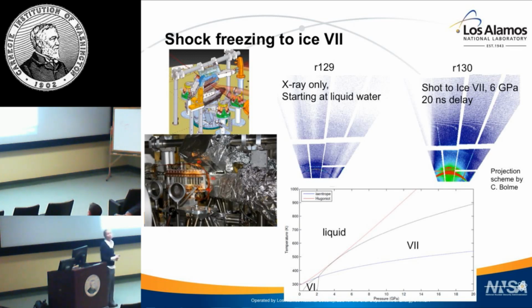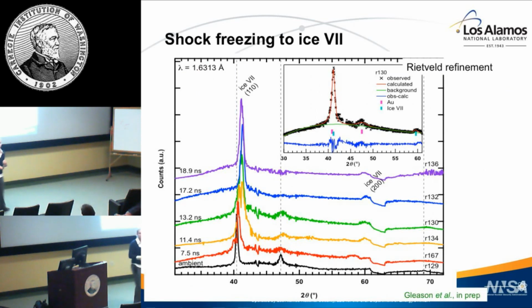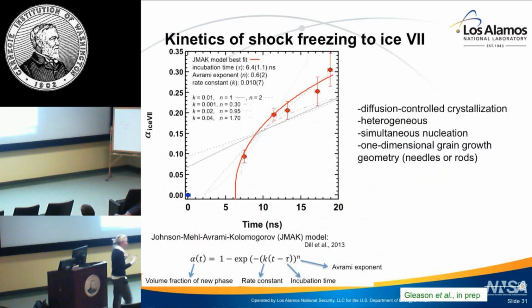Okay. Again, we can do Rietveld refinement. I want to stress that is really a new feature. Diffraction has been collected at other laser facilities, but really the opportunity to execute Rietveld refinement is this new piece coming from an X-ray free electron laser-based diffraction experiment. Utilizing Rietveld refinement, I can pull out phase fraction. If I can pull out phase fraction, it means I can relate volume fraction of new phase as a function of time and apply some very simple functional forms from classical nucleation theory to this phase fraction as a function of time.